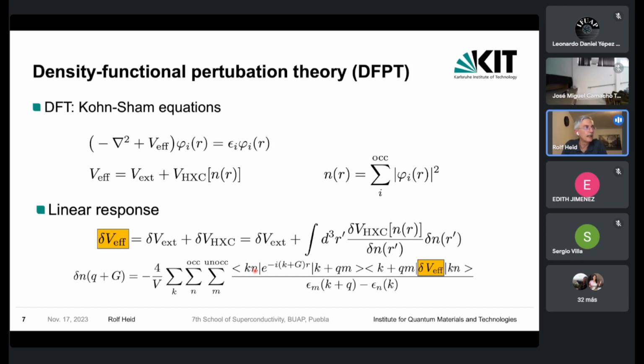Now, how can these quantities be calculated within a density functional based approach? This is very briefly sketched now on this and the next slide. In density functional theory, essentially one is dealing with the Kohn-Sham equations and one has to solve them, which are essentially wave equations for single particle electron wave functions moving in an effective potential. And this effective potential is described by a sum of two ingredients. One is the external potential, which in a bulk, for example, is given by the interaction of the electrons with the ions. And the second part is the screening part, or Hartree and exchange correlation part, which is a specific feature of DFT, and which is a function that implicitly depends also on the density itself. So one has to solve these equations self-consistently.